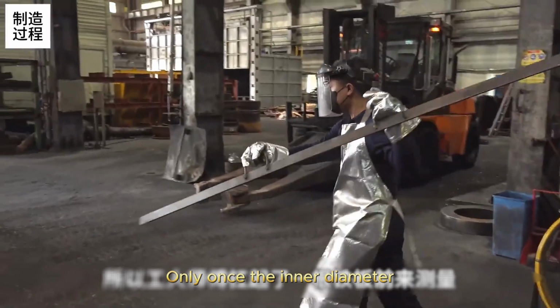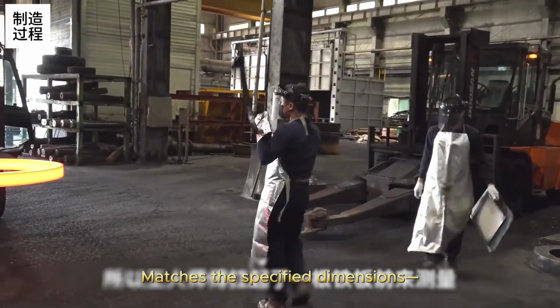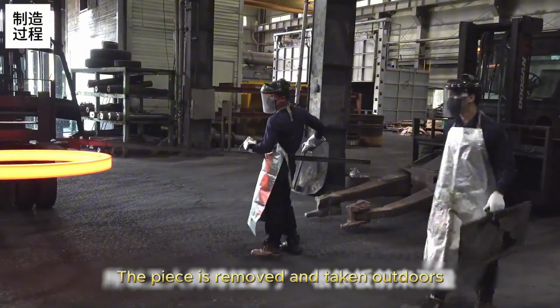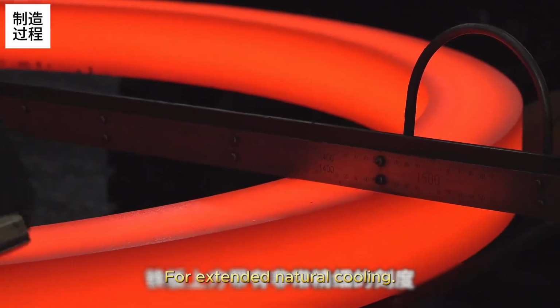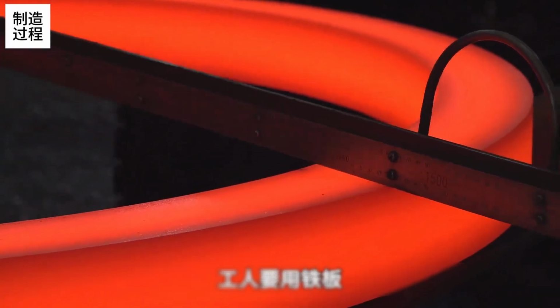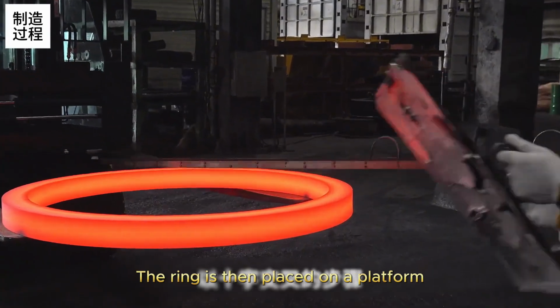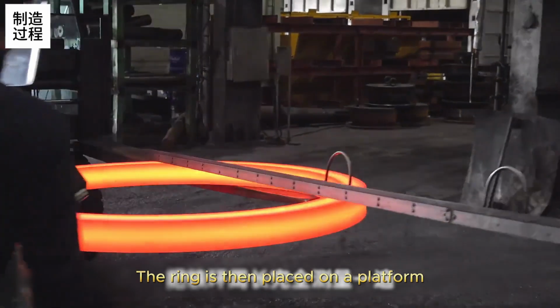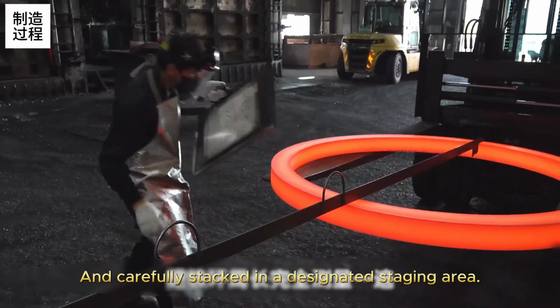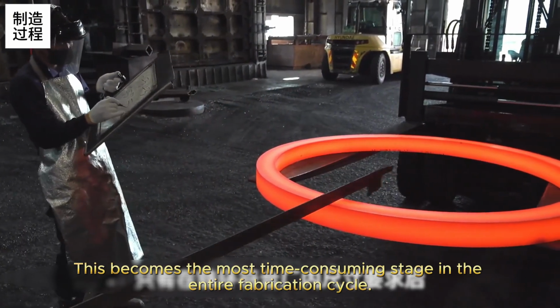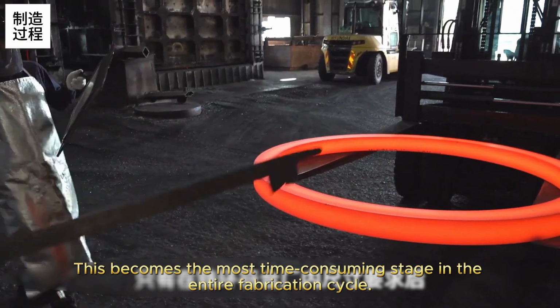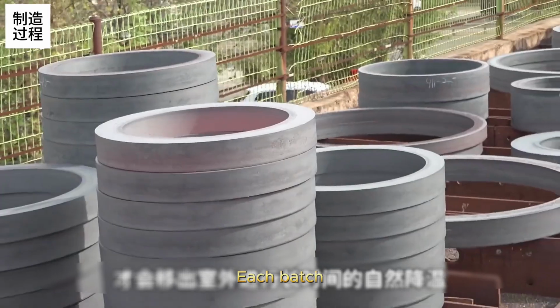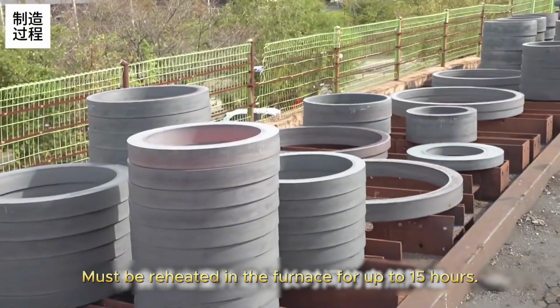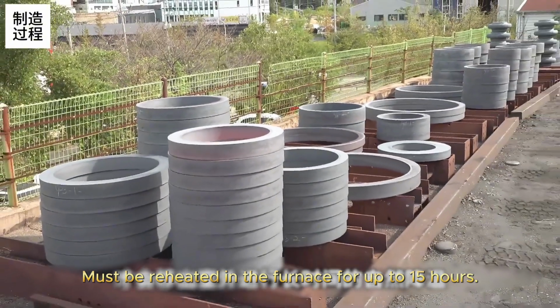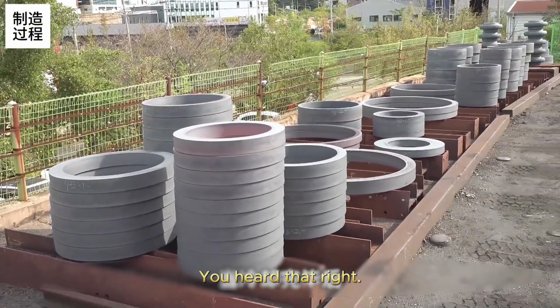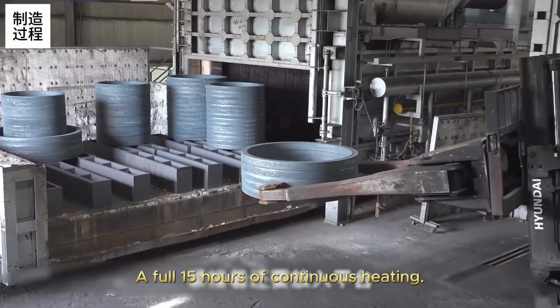Only once the inner diameter matches the specified dimensions, the piece is removed and taken outdoors for extended natural cooling. Once cooling is complete, the ring is then placed on a platform and carefully stacked in a designated staging area. This becomes the most time-consuming stage in the entire fabrication cycle. Each batch must be reheated in the furnace for up to 15 hours. Yes, you heard that right. A full 15 hours of continuous heating.